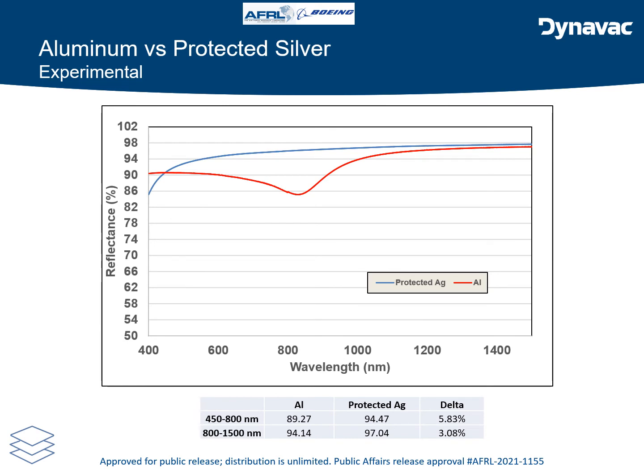This slide shows experimental results of aluminum and protected silver. And as we can see, protected silver has improved performance in the IR spectrum, and it also avoids the dip at 800 nanometer wavelength.